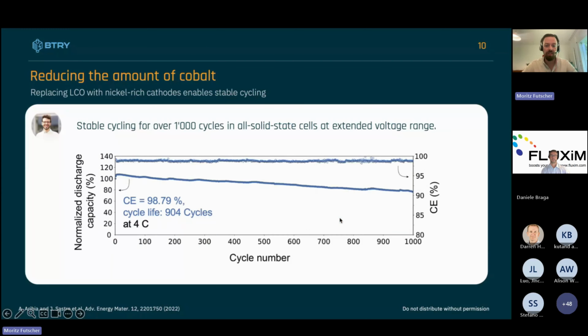And he also showed that this material in a solid-state configuration, we were able to cycle for more than 1,000 cycles, where in this case the cycle life is 904 cycles. This is usually defined in batteries as when the capacity reaches 80% of the initial capacity. So this was basically one of the starting points of one of the cathode materials which we developed in the research group, really replacing this LCO, which is frequently used.